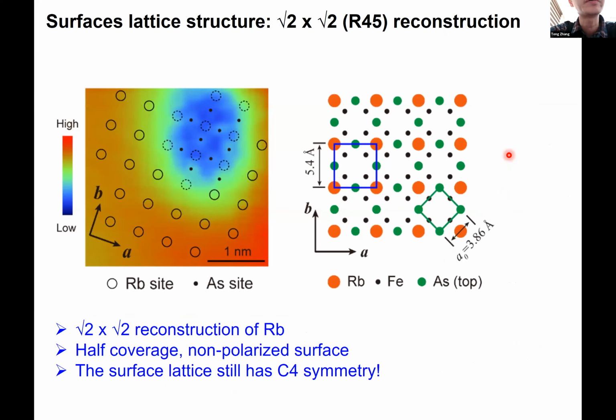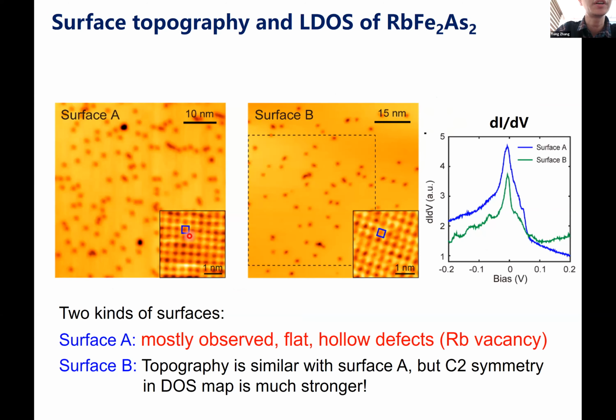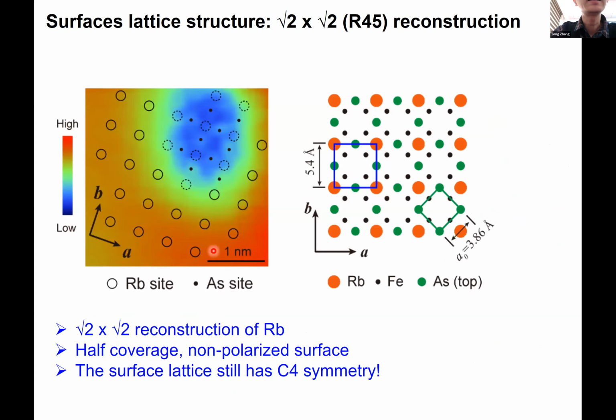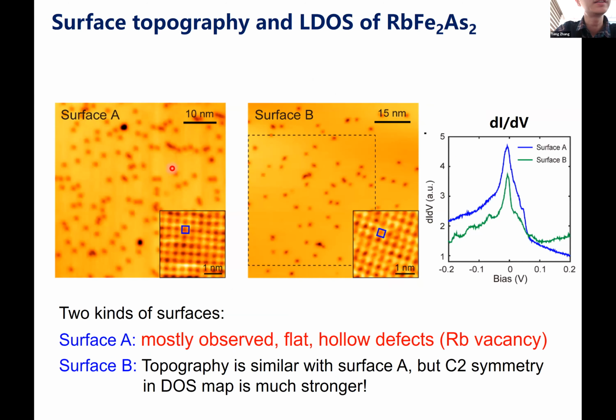So firstly, we should clarify the surface lattice structure. Here we can resolve the surface lattice. It is a square lattice. The lattice constant is about 5.4 angstroms, and it corresponds to a √2 by √2 reconstruction formed by the surface rubidium atoms. On the surface you can see a lot of hollow-like defects. They are actually rubidium vacancies. The smaller ones may be single vacancies, but the bigger ones are not single vacancies, but maybe 2 or 3.